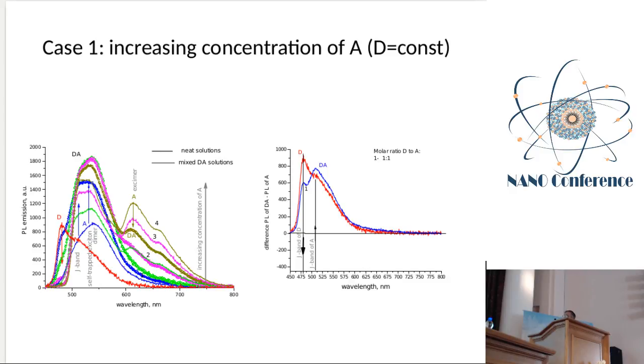Here, solid curves correspond to the mixed solution, and curves with circles correspond to the neat acceptor solution. What we can see is that in the mixed solution, the contribution of the donor J aggregates significantly reduces because they give up the energy to the acceptors. But excimer emission also decreases in the mixed solution. For example, you can compare these yellow curves. Excimer emission in the mixed solution is significantly lower than in the neat acceptor solution.